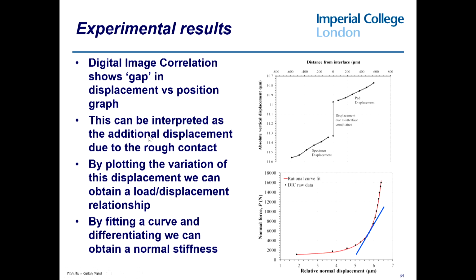So if you look at a pair of contacts, for example, you can see that the displacement in one surface follows this line, and we would expect the displacement to be continuous. But it isn't. There's this gap across the contact. And the reason is we've got this rough layer, which is very, very compliant. It's very, very springy. And we get this gap, and from that, we can plot that gap against the force, and we can generate a curve like that.